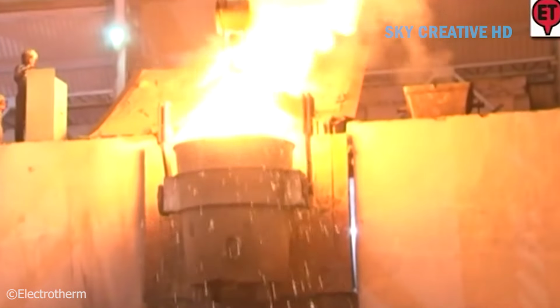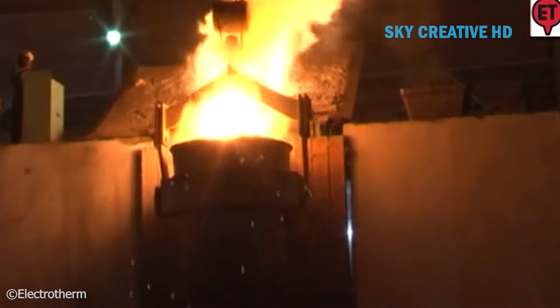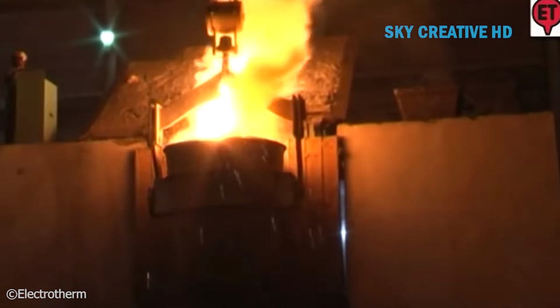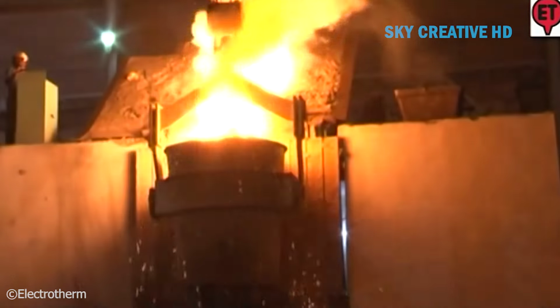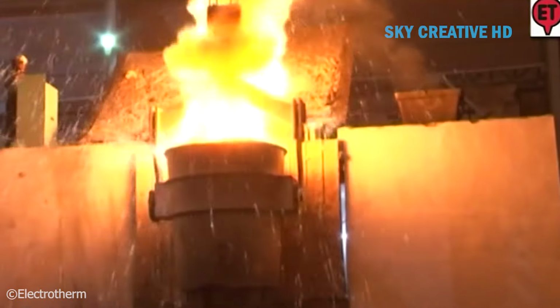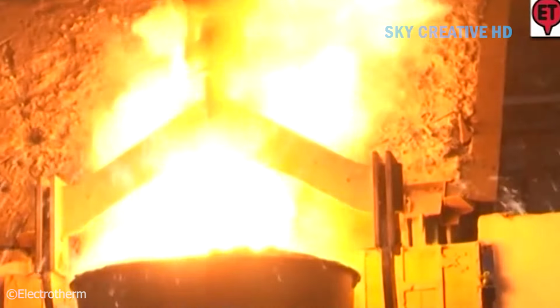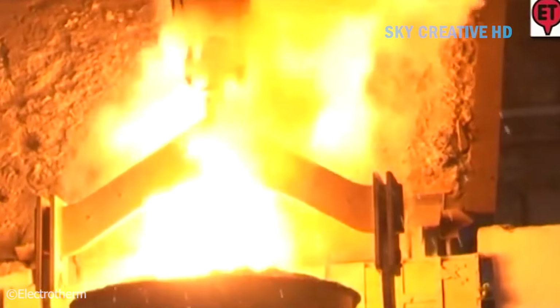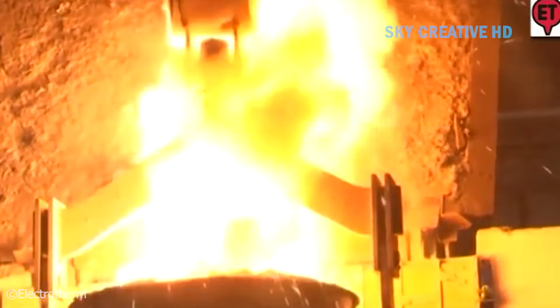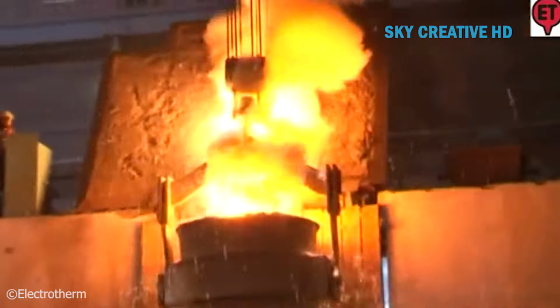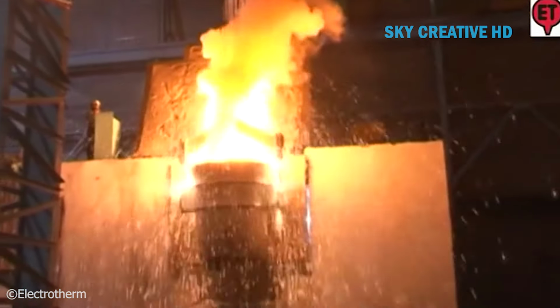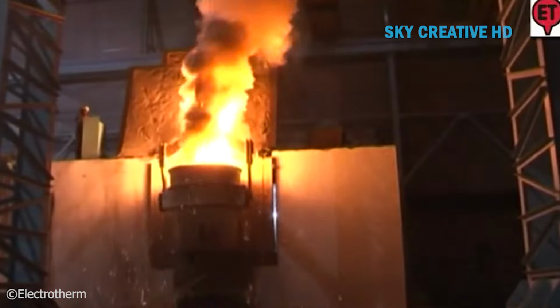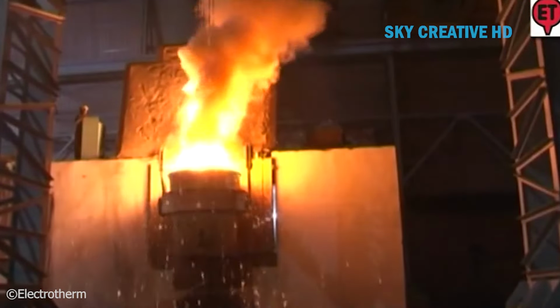Unlike vertical casting, where molten steel flows downward into water-cooled molds, the HSMC process casts horizontally. A water-cooled copper mold, oscillating back and forth to prevent sticking, receives the molten steel. The horizontal orientation offers several advantages. It eliminates the bulging and internal cracking sometimes seen in vertical casting, allows for better control of solidification, and permits easy adjustment of billet size without major equipment changes.